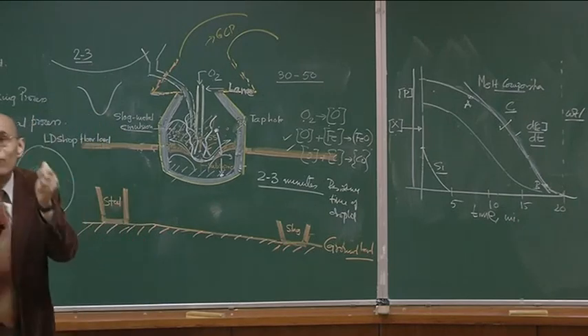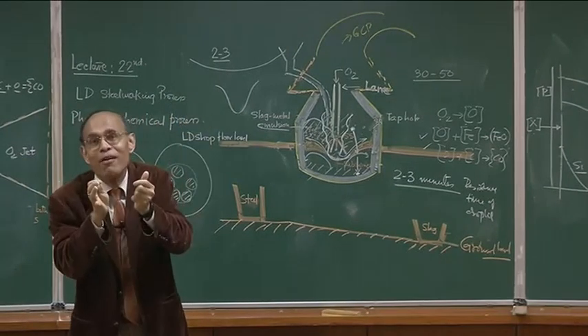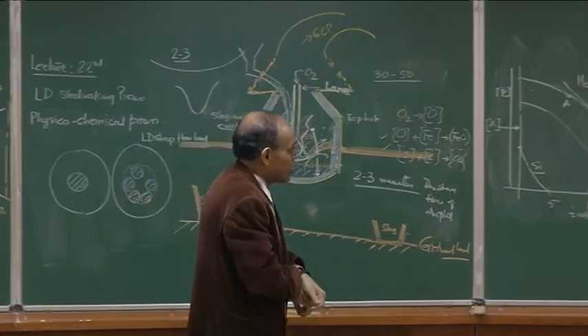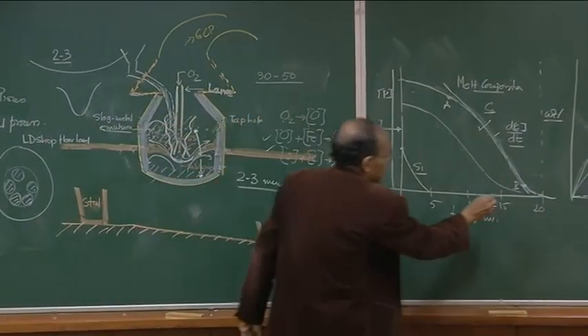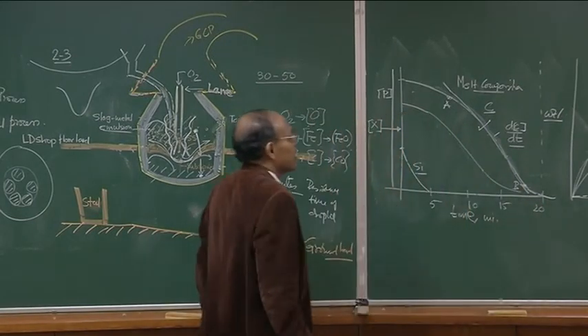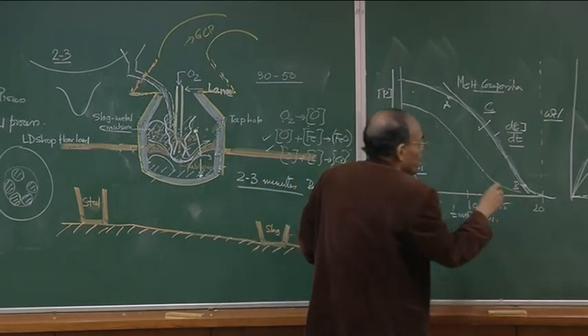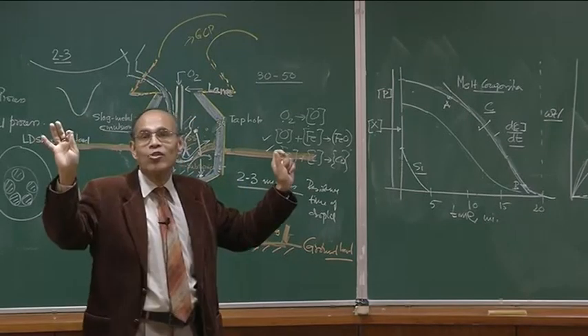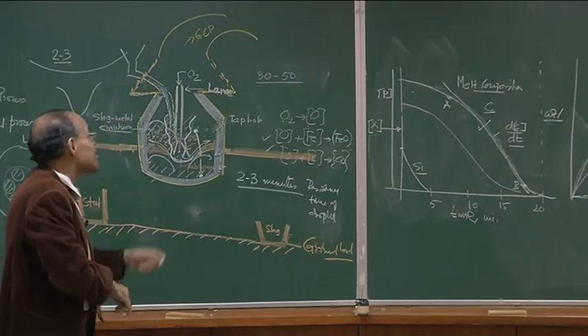Of course, fortunately, phosphorus has a very small value, not as much as 4.3% carbon, but only about 0.15 or 0.2 weight percent at the most in hot metal itself. So as we say, the phosphorus removal is completed before the emulsion collapses, or by the time the steady decarbonization period is over, the chemistry sampling indicates that we have been able to. But it is not so easy.